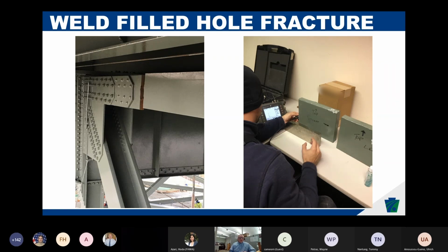I put this in here because it's always a good idea when you get into those one-off circumstances, those one-off situations where it's not covered in any code, it's not covered in any type of specification, to make some type of demonstration block or mock-up block to perform a practice test to make sure that you can find what you're looking for. There's nothing in the codes that would address these weld-filled holes currently. So that's exactly what they did on this project. Like I said, I spent a day down there just playing around with these blocks, and they made them pretty difficult to locate the weld-filled holes, to mimic those weld-filled holes. And they were actually qualifying inspectors to go on the bridge with these plates. If they couldn't find it in the test blocks, they weren't allowed to be on the bridge testing.